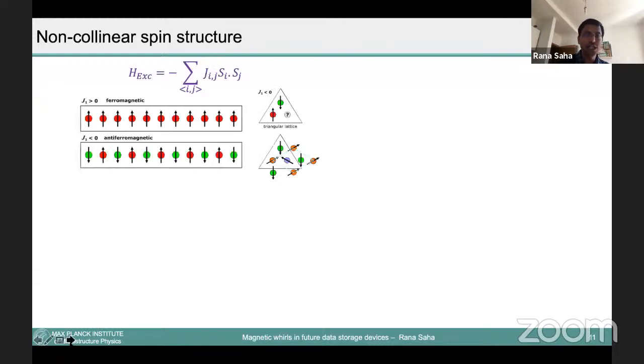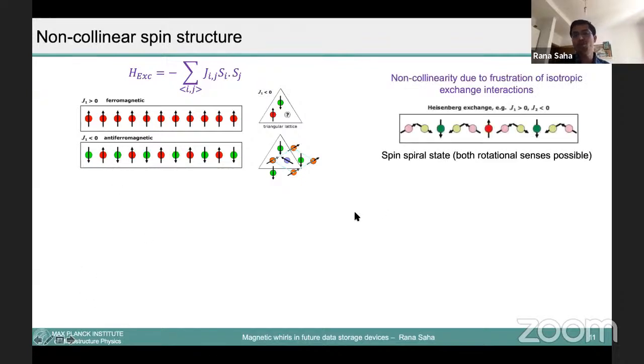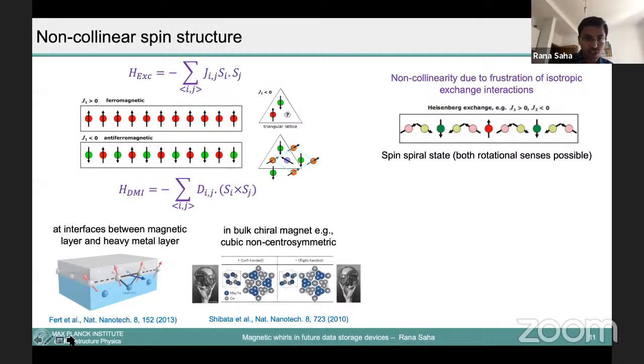This racetrack memory can also use, as I showed with the one-dimensional domain wall, some kind of non-collinear spin structures. These are parallel spins in a ferromagnet or antiferromagnet, and because of frustration you can also have some non-collinearity. But we are interested in a chiral non-collinear structure.